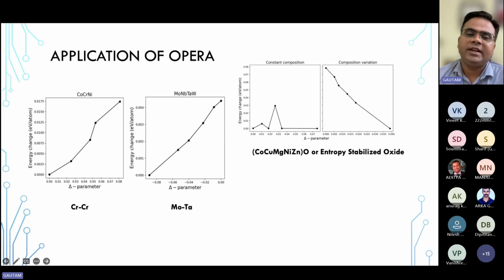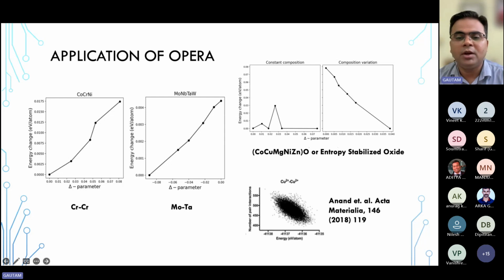As you can see, these are all constant composition cases, and the energy doesn't show any trend. We're not comparing it per se; in this particular case, we're just increasing the copper cation propensity in this entropy stabilized oxide. We were able to come up with a prediction that if you increase the copper propensity, you increase the energy of the system, which we have earlier predicted. So it can be applied to any kind of high entropy material.